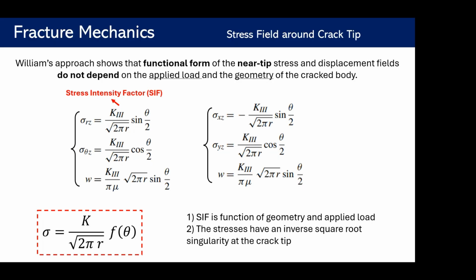But it goes toward infinity proportional to the inverse of the square root of r. It's always the same. The function of r is always the same, but we have different f of theta for different modes. You can see here the f of theta for just third mode.